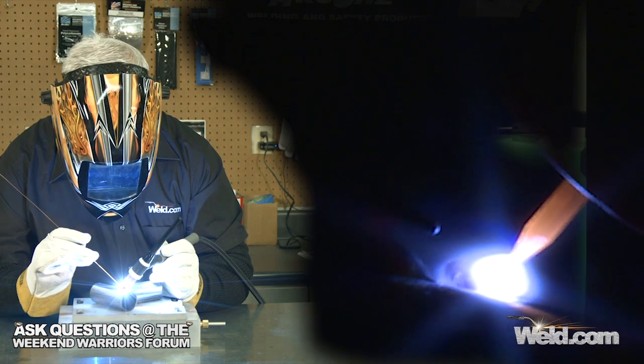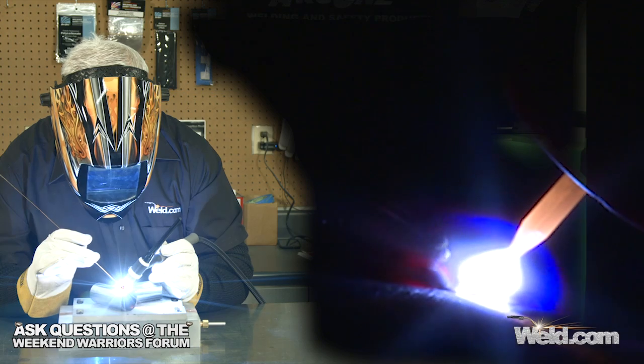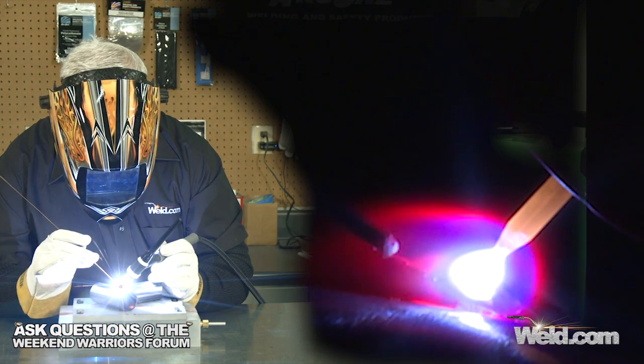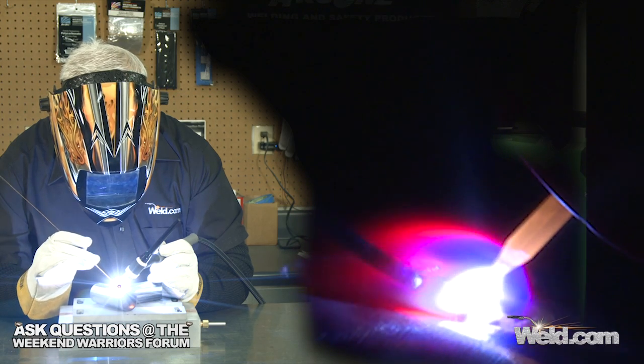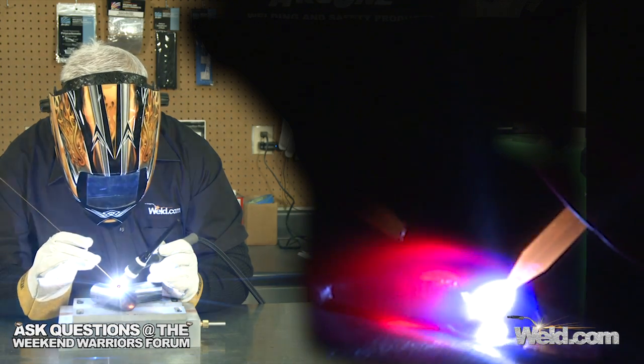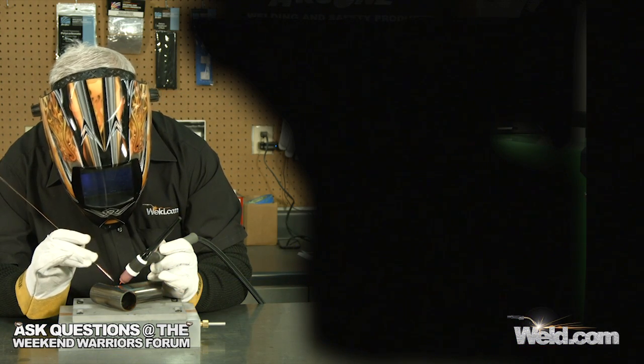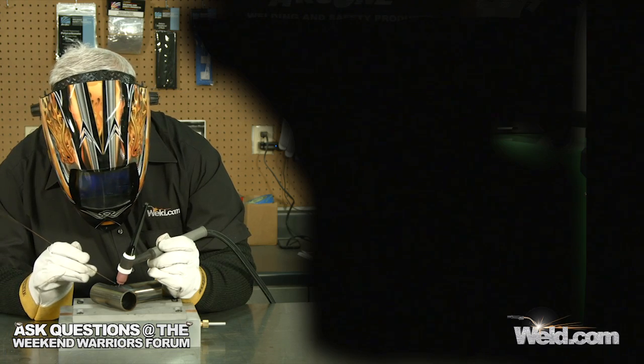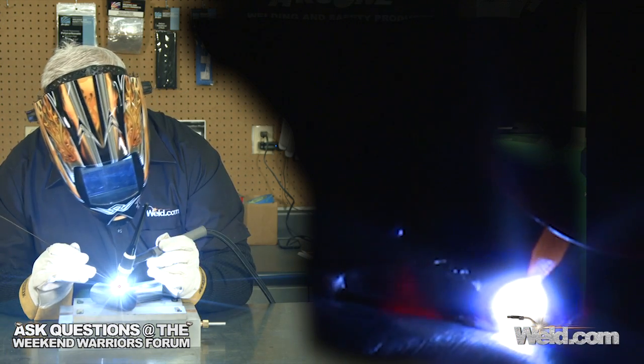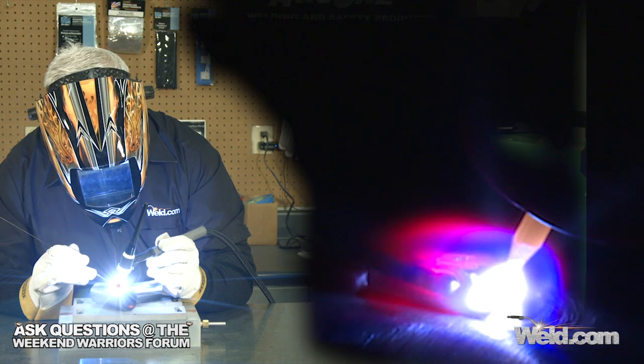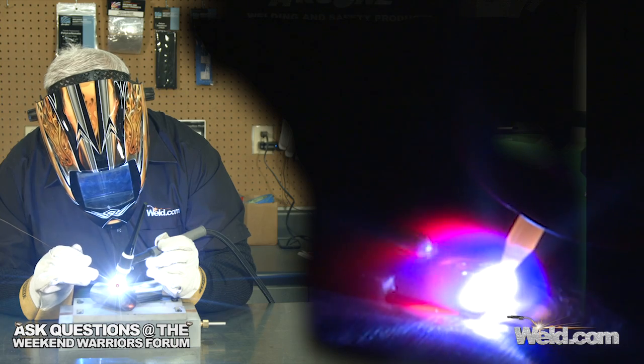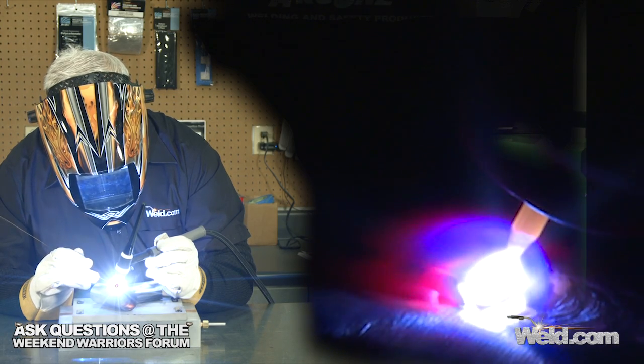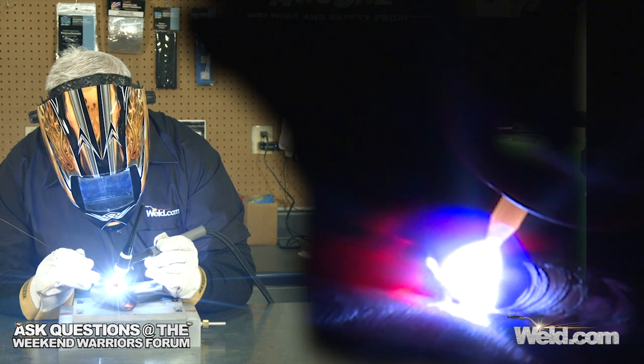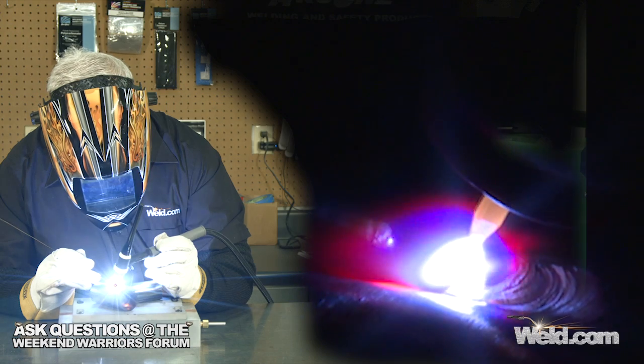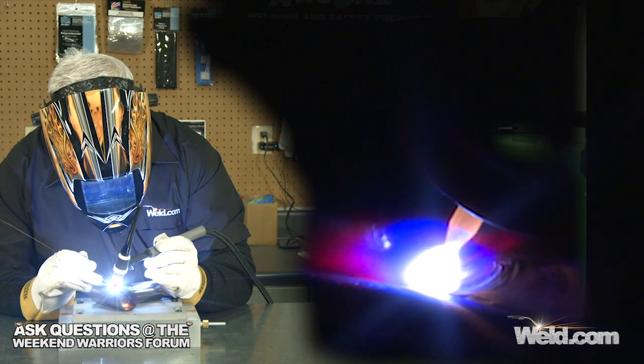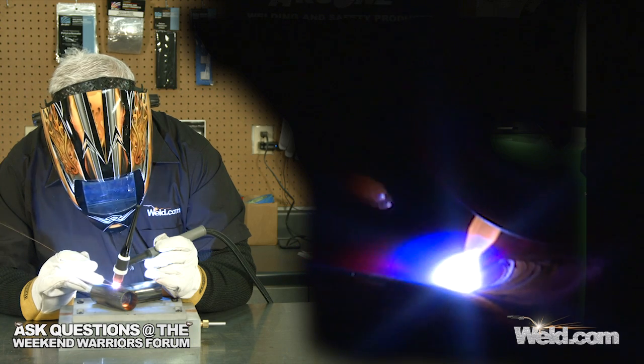Okay, I'm doing one of the final welds on here. I'm doing this with the DC straight polarity. My filler material is just 0.045 diameter. And you can pretty well choose the diameter that you like best. Running argon, I'm at about 15 to 17 CFH of argon. It welds really clean.